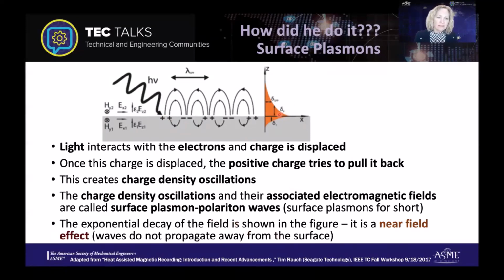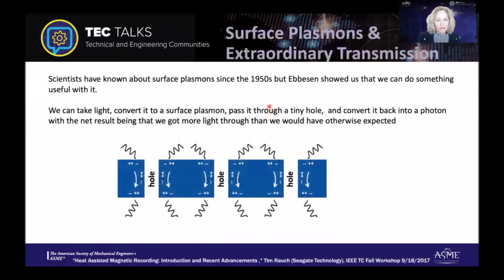And they actually create this electromagnetic field as a near field. So you can see the decay of that field here. It's not a propagating field. That field is only present within tens of nanometers of that surface. And so the field is only going to be active when we're very, very close to the surface of that material. People had known about surface plasmons since the 1950s, but Ebbesen was really the one to show that you could do something useful with it.